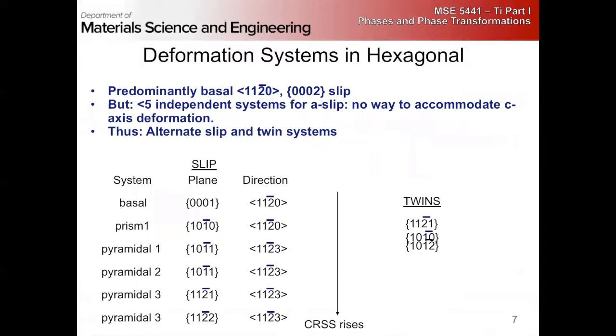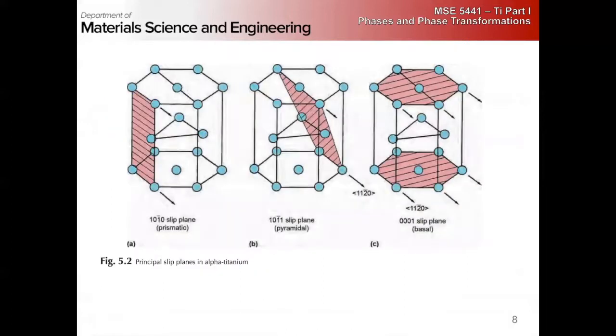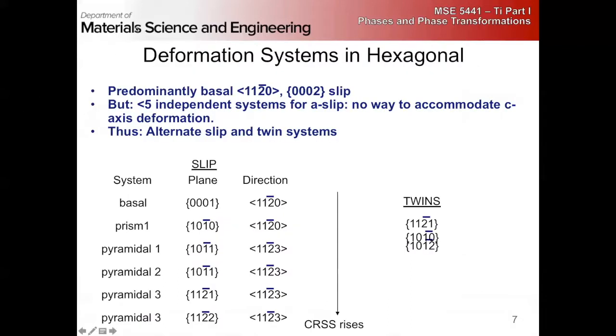Okay, so slip, so what are our primary slip systems in HCP? What are our close-packed planes? The basal planes. And our close-packed directions, so that's a natural slip system. What other planes have the close-packed directions in them? The prismatic planes, the 10 bar 10 planes.